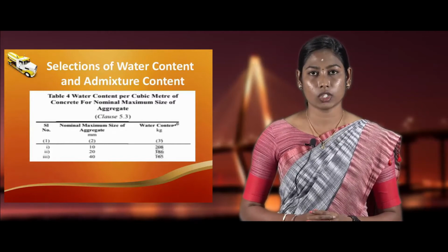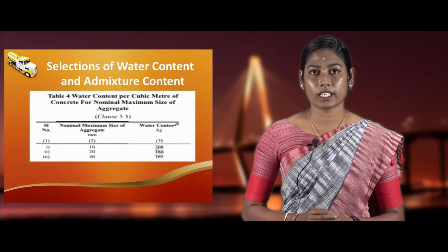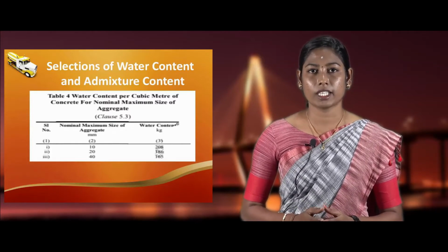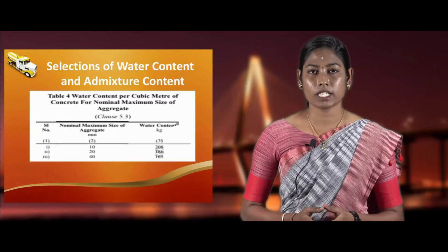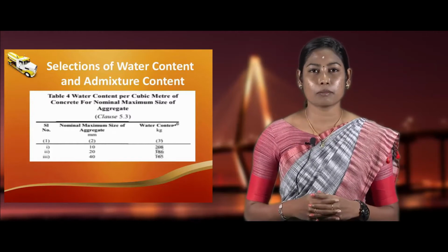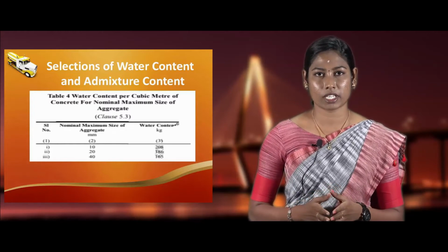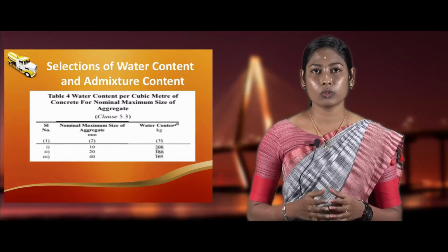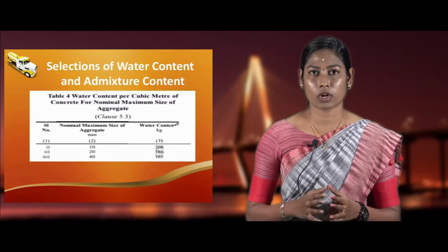The water content in concrete is generally affected by various factors such as aggregate size, aggregate shape, aggregate texture, workability, water cement ratio, cement content and other cementitious material, and environmental conditions. As the maximum size of aggregate increases, a reduction in the water cement ratio and slump, and the use of rounded aggregate and water reducing admixture will reduce the water demand.